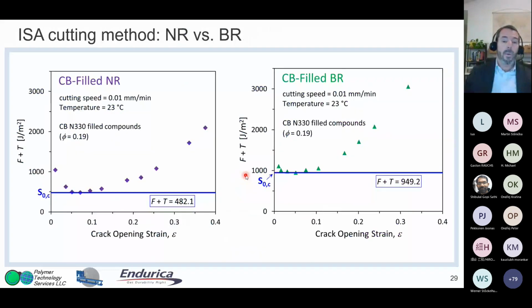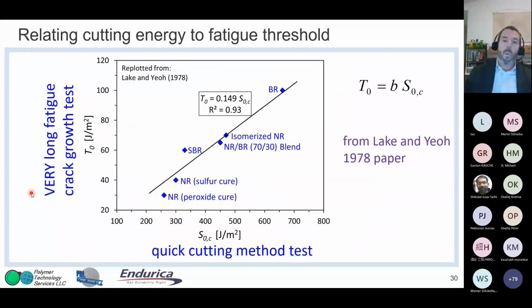So you can see that we don't have T0 yet. We have this so-called S0. So what Lake and Yeoh did, they plotted the quick cutting method value that I just showed you, and they compared it to T0 that was measured from that near threshold, very long fatigue testing that I showed you an example from Dr. Stocek earlier. And what they saw was that these were related to each other. And the difference was this constant, which was related to the blade, right? How sharp the blade is, etc.